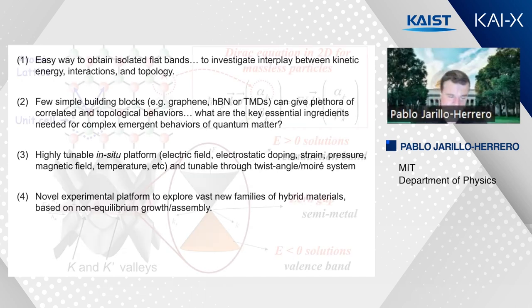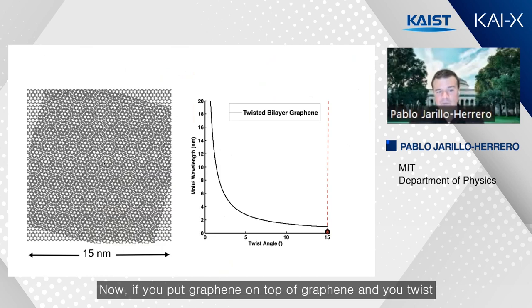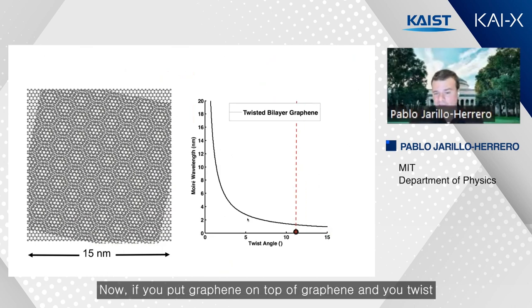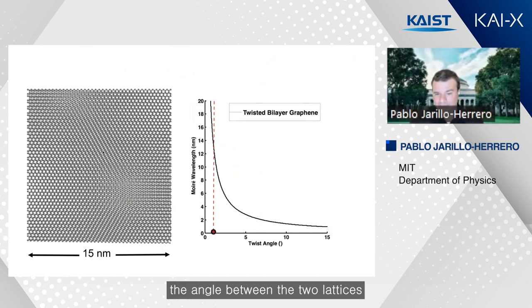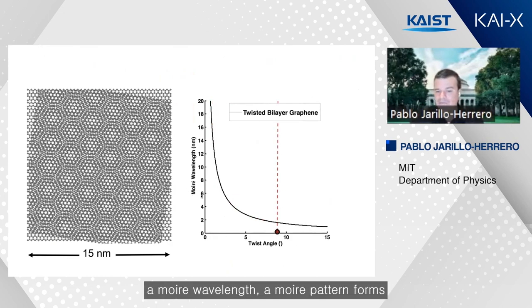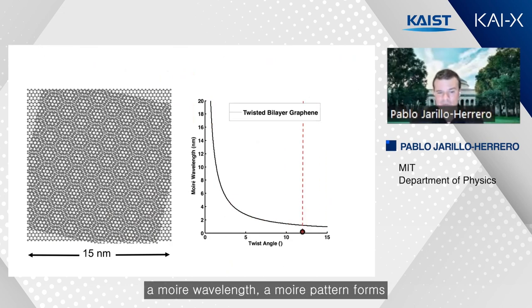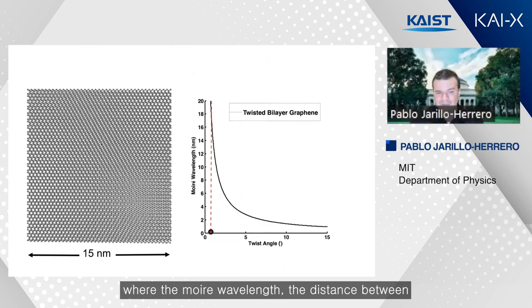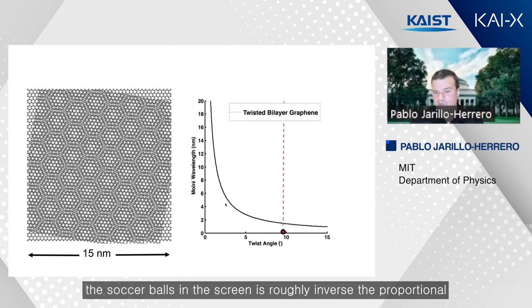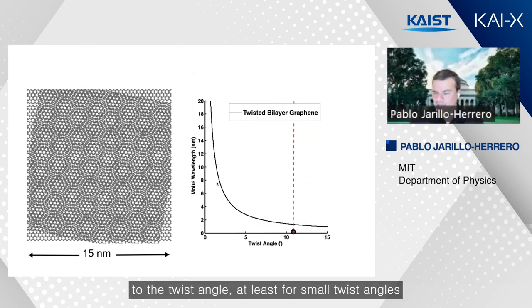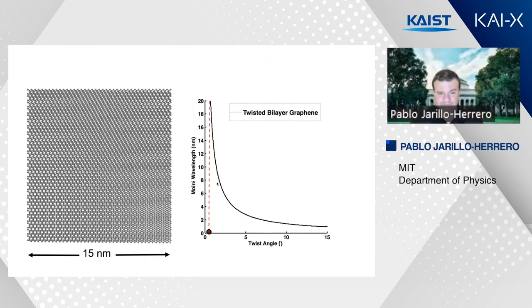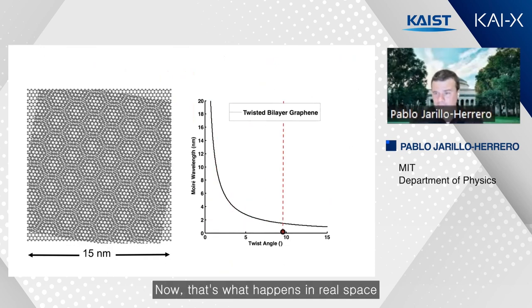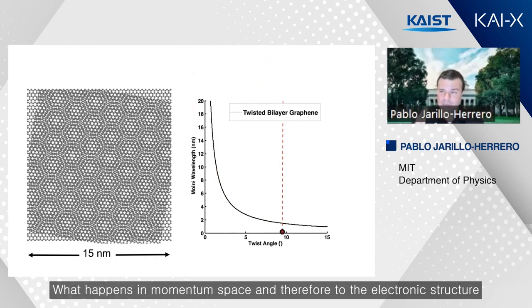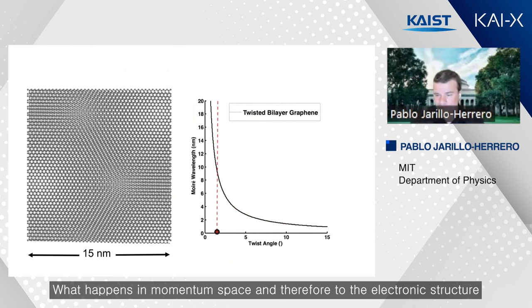assembly. Now, if you put graphene on top of graphene and you twist the angle between the two lattices, a Moire pattern forms, where the Moire wavelength, the distance between the soccer balls on the screen, is roughly inversely proportional to the twist angle, at least for small twist angles. Now, that's what happens in real space. What happens in momentum space, and therefore to the electronic structure?